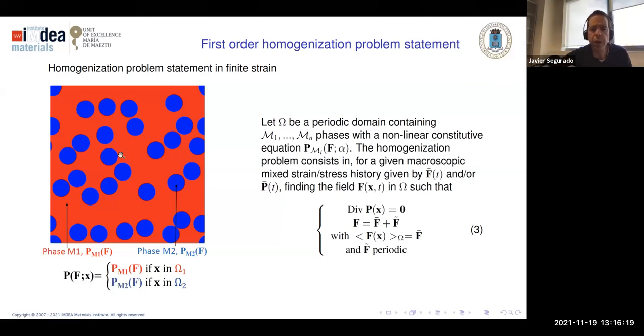We know that the macroscopic applied strain is just the average of the microscopic strain, and the same in terms of deformation gradients. This is the Hill-Mandel statement, which is fulfilled here due to the periodicity. The problem is then that we want to find the stress fields that are in equilibrium such that the strain at every point fulfills the homogenization, where the fluctuations are periodic, the same on the left and on the right, and the deformation gradient is compatible.